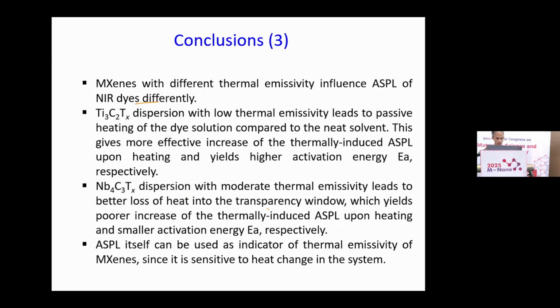So, conclusion concerning this last part of my presentation. I showed you that MXene with different thermal emissivity can influence anti-Stokes emission of near-infrared dyes differently. And specifically, titanium MXene, which possess low thermal emissivity, leads to the passive heating effect, and this yields higher activation energy of infrared dyes. On the other hand, niobium MXenes have moderate thermal emissivity, which results in smaller activation energy of our infrared dyes. And finally, anti-Stokes photoluminescence itself can be used as indicator of thermal emissivity of MXenes, because this process is sensitive to heat change in the system.